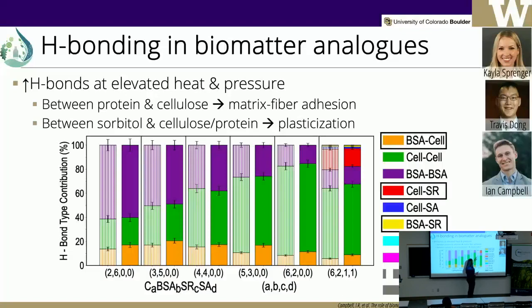Then we also see another interesting fact. The sorbitol and the cellulose are going to be interacting with themselves, actually giving a significant proportion of the hydrogen bonding amount, even before the hot press.